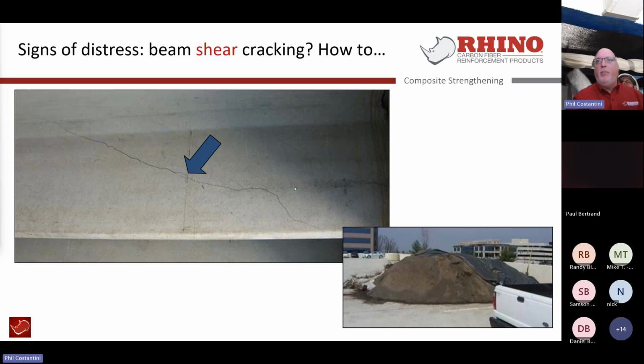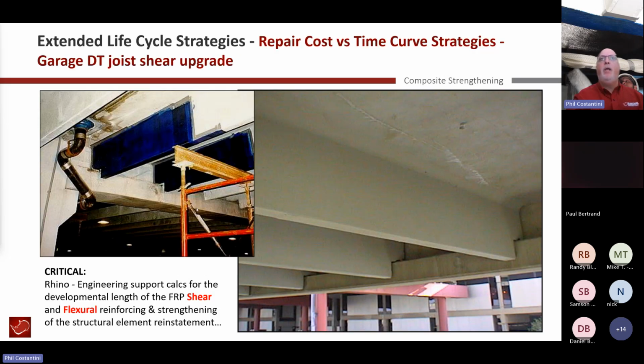And because this was a relatively brand new parking structure, it wasn't designed for accepting this type of load. And of course, he overloaded it right at the edge, which caused this diagonal crack. It was caught in time. Let me repeat myself. It was caught in time to prevent any post-shoring requirements, but we were able to come up with a similar methodology to what we did with the roof beam, using carbon fiber, and detailed the repair costs and the time curve strategies to reinforce that double T and get it back into service. So this was strictly an FRP shear and flexural reinforcing for that structural element, and it was reinstated.